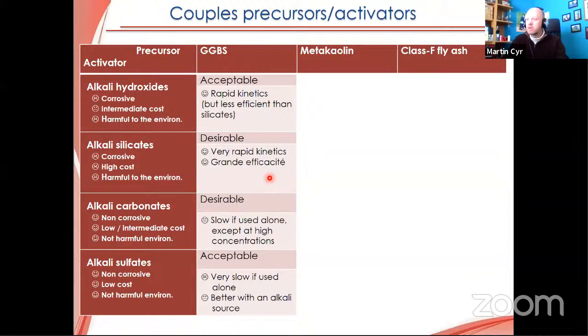I forgot to translate some parts. Great efficiency. But sometimes we have some problems at young age when we are using this kind of activator because we have a very short open time, meaning that we only have sometimes maybe half an hour if we don't mix the GGBS with something else. Alkali carbonates are working quite well also, but a little bit slow if they are used alone, except at high concentrations. So sometimes we try to mix some activators together to be able to have good properties.